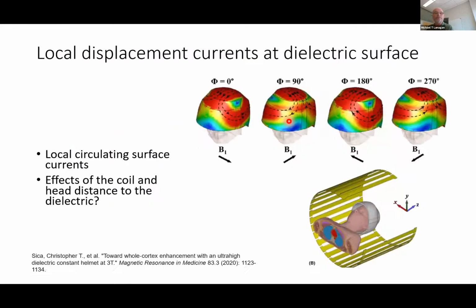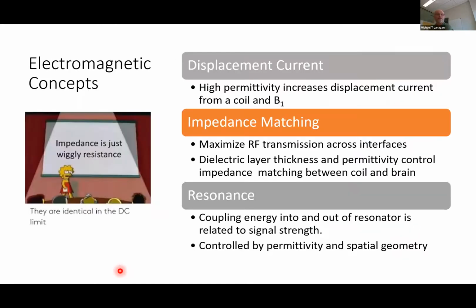And of course, if we go from that dielectric block to something like a helmet that I showed, we're really looking at these displacement currents in this way. We've done a lot of simulations to really optimize the helmet dimensions and the permittivity values to couple with these different coil configurations within MRIs. And there's several publications. Another one is shown here. So that's one of the things.